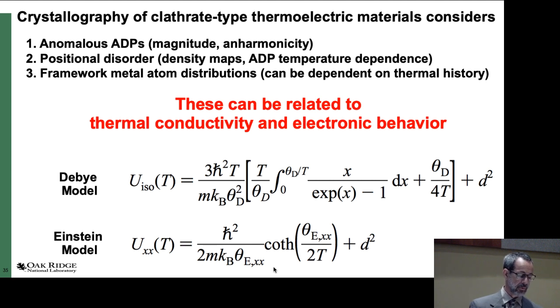So all of these then relate to the thermal conductivity and electronic behavior. We have developed, with Bryan Sales, some recipes to compute lattice thermal conductivity and other thermodynamic properties based on the Debye model for the framework atom displacements and using Einstein models for the caged atoms, which became very popular.